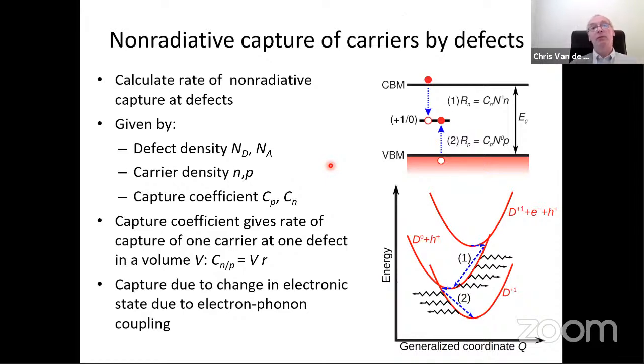So in the next few minutes, I want to tell you a little bit about non-radiative recombination. Okay, so the radiative recombination in configuration coordinate diagrams such as this one involves these vertical transitions that are induced or involve photons. Non-radiative recombination does not involve photons. It involves going from one state of the defect to another lower energy state of the defect, essentially by crossing over from one curve to another using energy available in the lattice. And if you think about this semi-classically, you would say, well, okay, all I need to do is go over an energy barrier to be able to get to this lower energy curve.